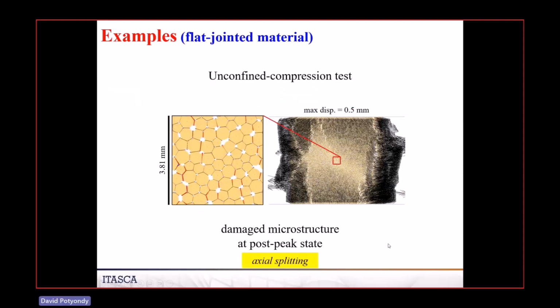This is showing that we have axial splitting during an unconfined compression test. This is the displacement field of the macroscopic specimen, and those little arrows are the displacement arrows of each ball, and you can see very clearly that this part is popping out and this part is popping out, so it's actually splitting on the sides.